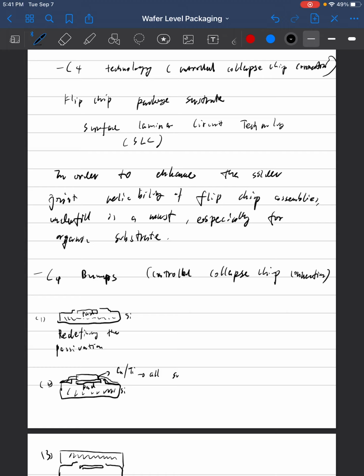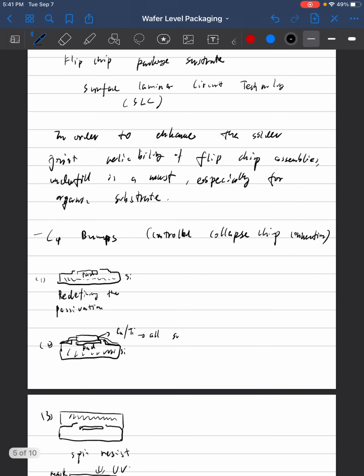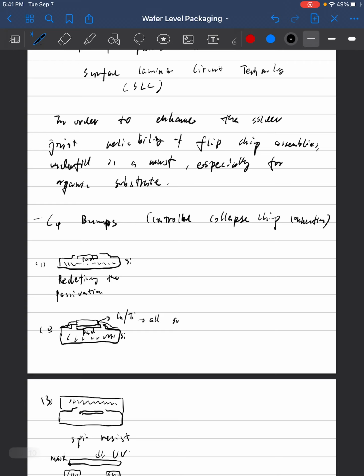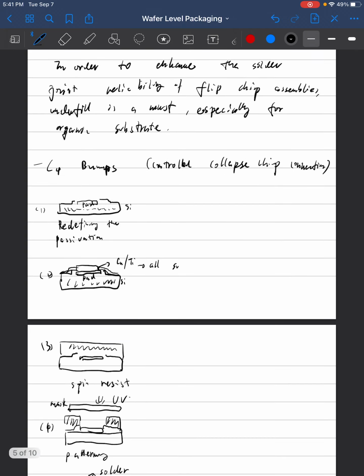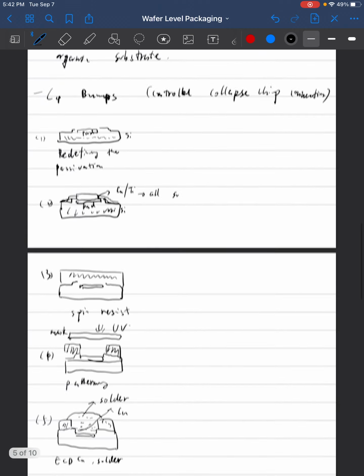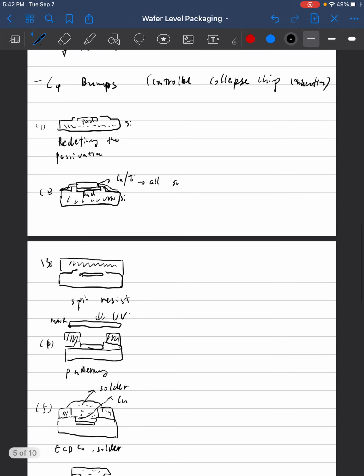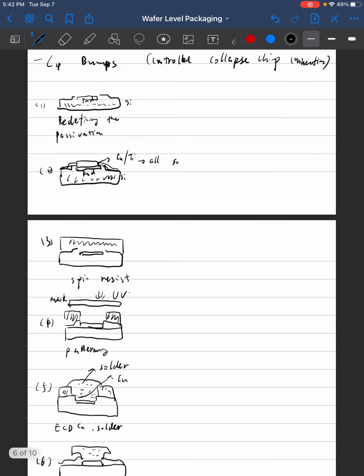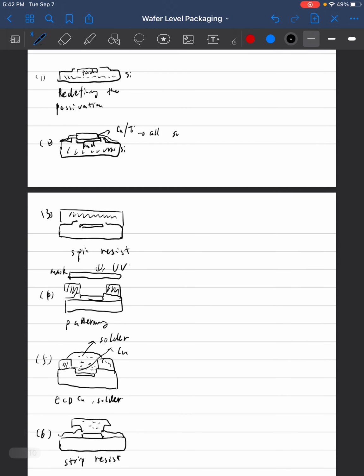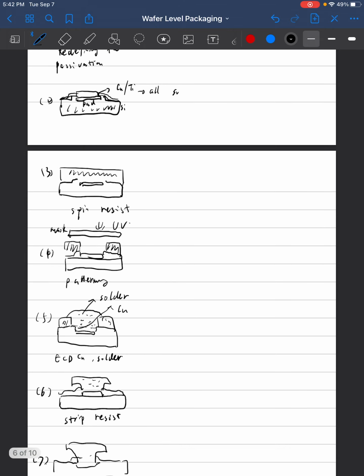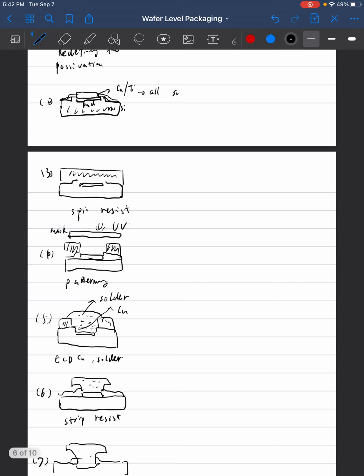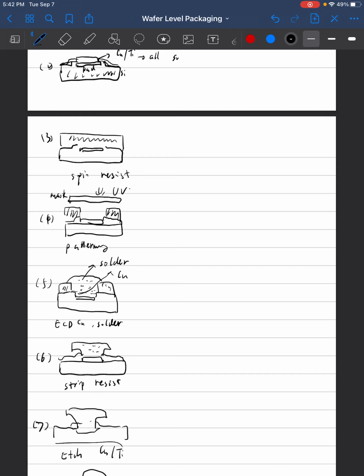In order to fabricate this kind of interconnection, for example, let's say C4 bumps. First, we need to redefine the passivation for the pads, and then we deposit copper and titanium all over the surface. Then we spin photoresist material on top of the wafers. Then we use a mask and UV light to do the patterning and etch away the center place. Then we use the electrochemical deposition method to deposit copper and solder sequentially into the holes. After that, in this process, we use a little bit more solder to form this kind of mushroom structure. After that, we strip away the photoresist.